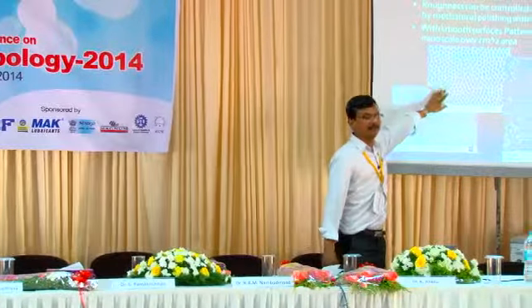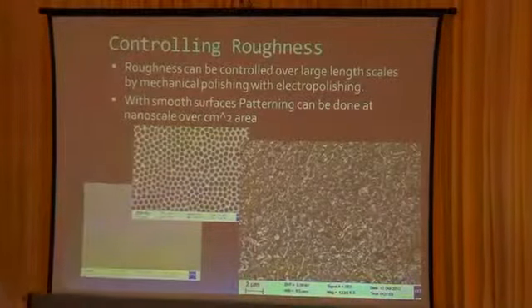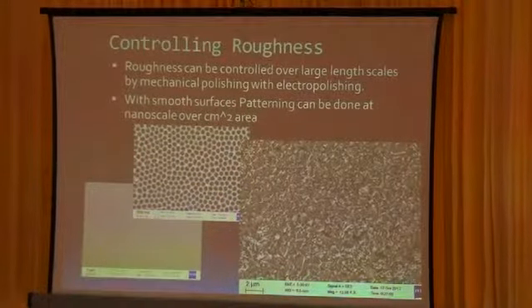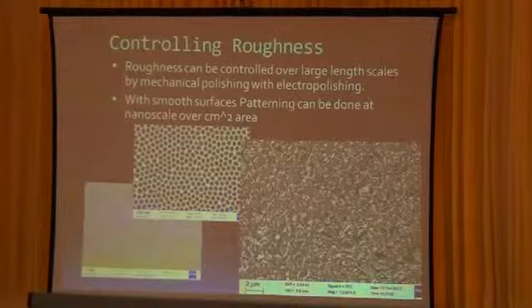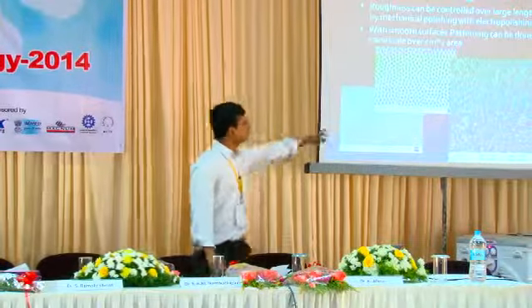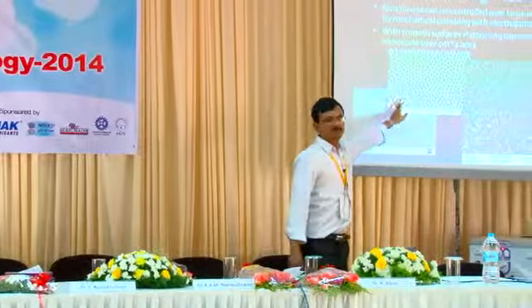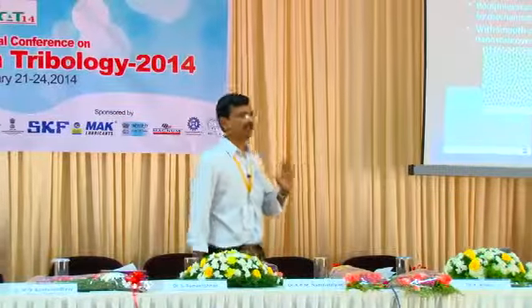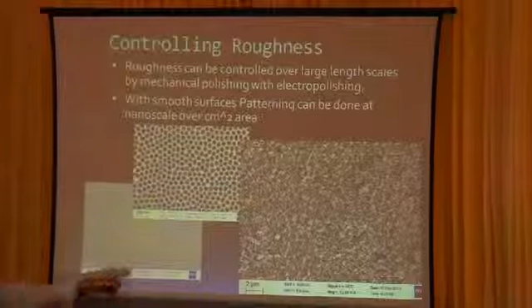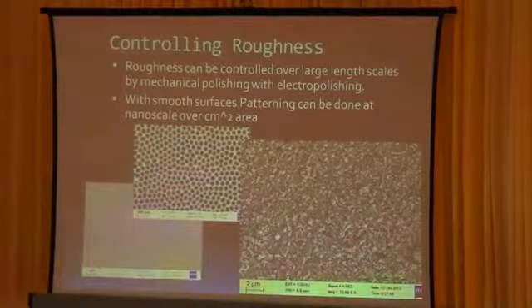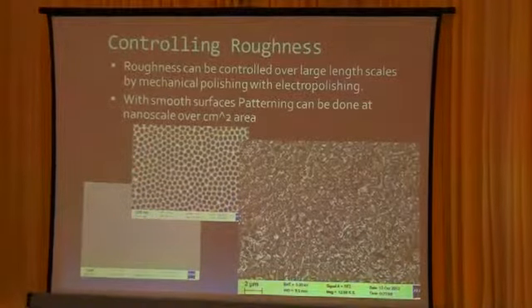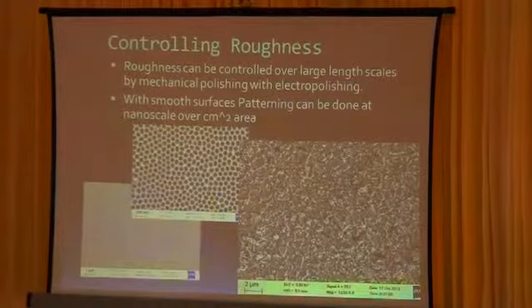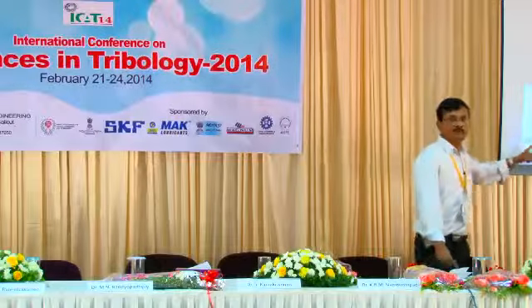This is a porous alumina. You see, this pore size is of the order of 50 to 70 nanometers. They are holes, and they are about a micron to 10 microns deep. We can control them, and this is what we managed to do in our lab. This is being done by chemists. A lot of chemists are doing it, right? What we managed to do, because we understand the roughness so well, like electropolishing as well as mechanical polishing combined together, was to do it over a very large surface area. Now we generate this porous structure over centimeter by centimeter, uniform. Okay, you can see the pores.